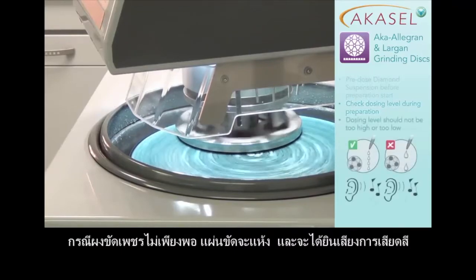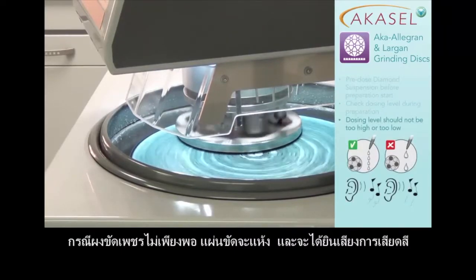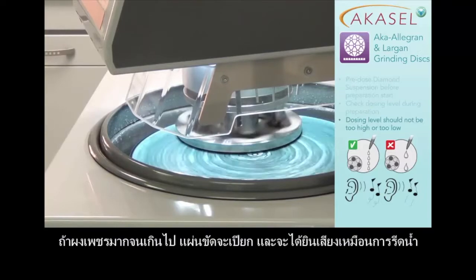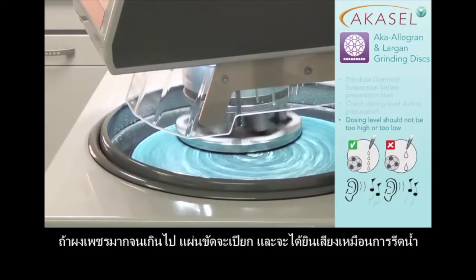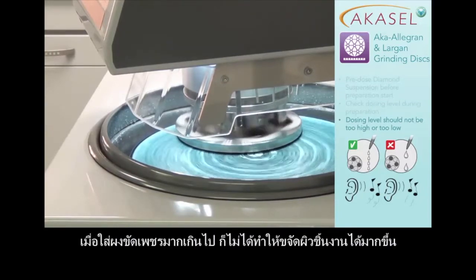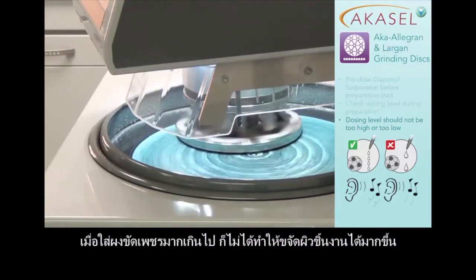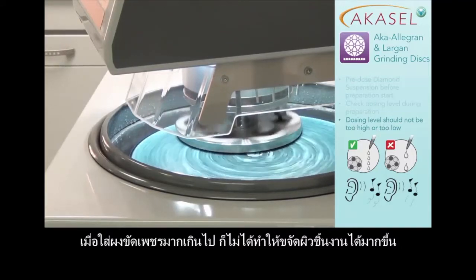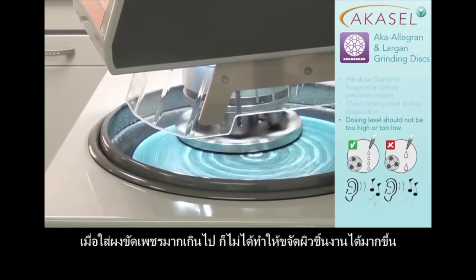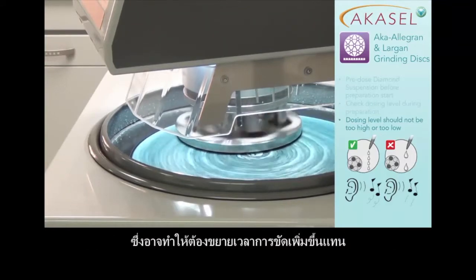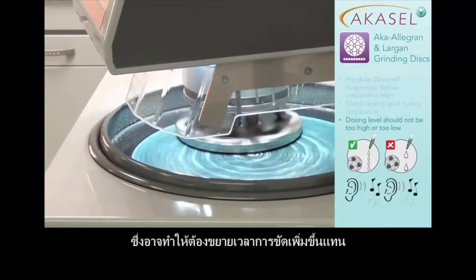If you do not have enough suspension, you will probably hear a squeaking sound. If it is running too wet, you will have a rattling sound. When you apply too much suspension, you will have some kind of aquaplaning effect. Even though you use a lot of suspension, you will not have a very high removal, so you will have to extend the preparation time.